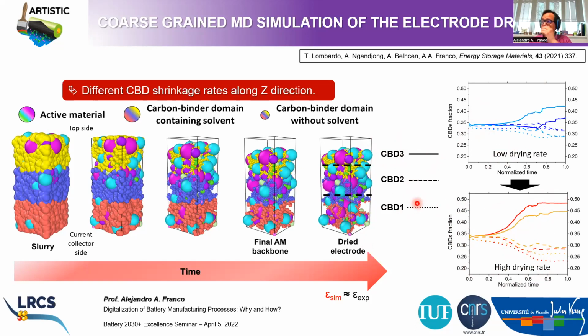And this is actually explained because when you apply high drying rates, you favor the motion of these particles, and then CBD is much more mobile and can go more to the top because of convection forces, right? Whereas when you apply low drying rates, you give time to the system to calibrate more nicely, and then the structure will be more homogeneous. So we have less deviation or less gradient of CBD volume fraction along the electrode thickness, right?